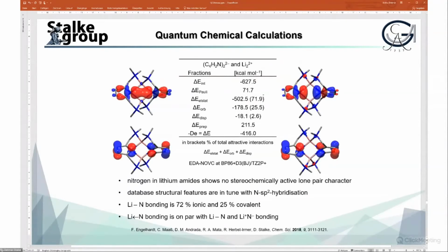So what is the contribution of the various energies? And there the Tonner-Frenking approach to the energy decomposition helps a lot, where we can calculate the contributions to the overall interaction energies. So electrostatics is overwhelmingly the contribution to the lithium organic, to the lithium amide bonding, so 500 kilojoule per mole.